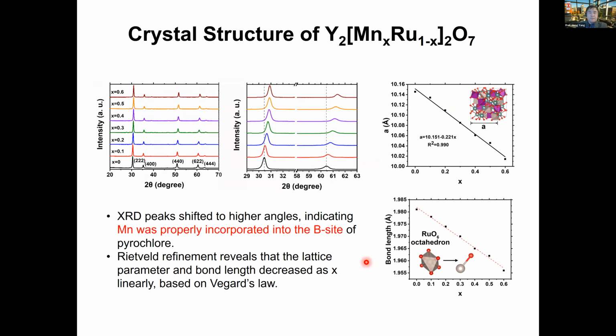What we have observed here is that we can dial in the manganese at very different ratios. If you look at the X-ray diffraction, we can dial in the manganese all the way above 50%, 0.5 in this regard, and that leads to practically a 50% arrangement between these two sites. Of course, we can even move this further to 0.6. If you look at the X-ray diffraction peaks, they shift almost monotonically with the composition change. This was also examined based on the angle change as a function of the amount of manganese doping, and this also correlates with the lattice changes.